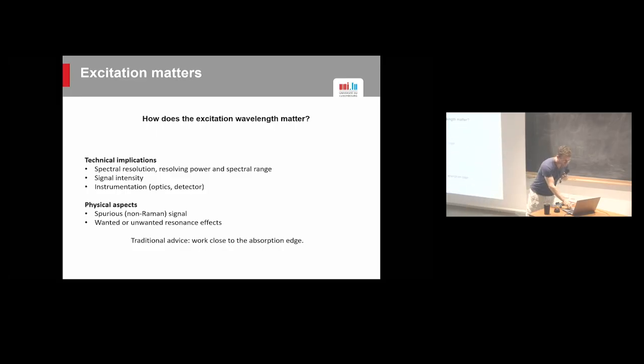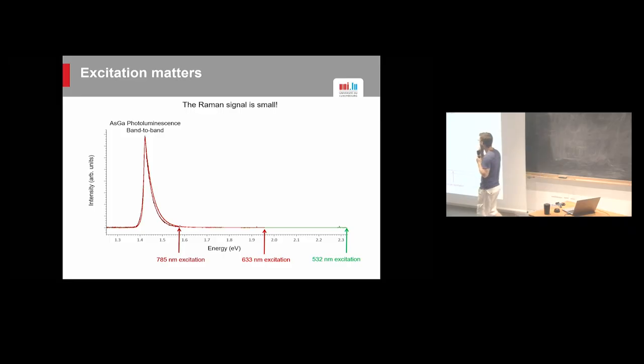And this is where typically I like showing this very much. So this is something we measured on our Raman spectrometer. It's gallium arsenide, okay, so not a perovskite at all. And we measured it with three excitation wavelengths. And here it's not Raman shift, okay? It's just the absolute energy of the photon that you measure. So this is measured with a green laser, this is a red laser, this is an infrared laser. And this, of course, at an energy of 1.4 or something, is the photoluminescence that comes from just the band gap emission of gallium arsenide. Okay, so of course, we know it should be there, right? But this is not what we are looking for. So where is the Raman?